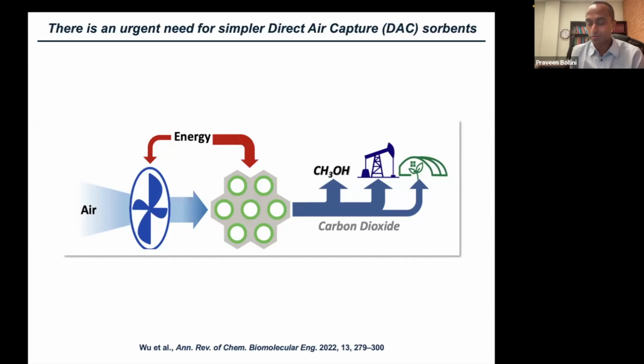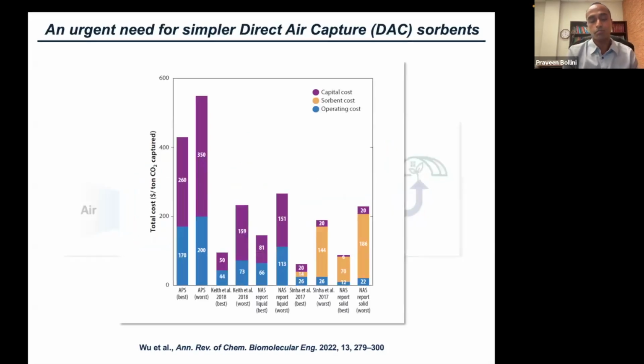I'm using direct air capture as an example because it's, in a lot of ways, at least from a technical standpoint, the most challenging of the carbon capture applications. So the basic idea is that you take air and you flow it over typically a solid sorbent, and you concentrate CO2 using this tool, either for sequestration or for further use, for example, to be converted to a value-added chemical product like methanol.